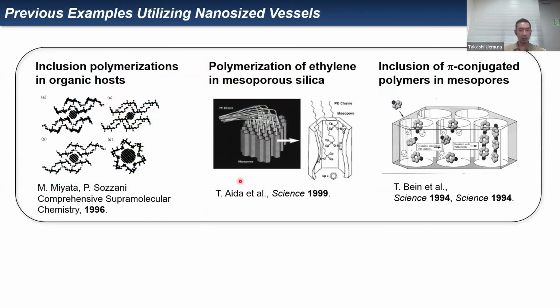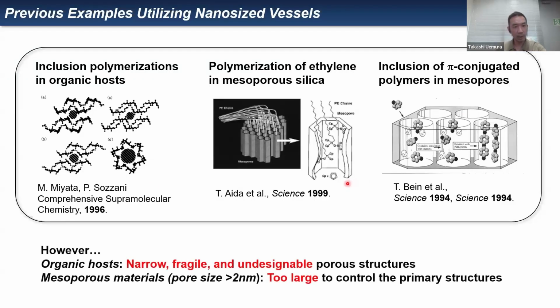Of course, this type of polymerization has already been reported using organic hosts and mesoporous silica systems. However, in the case of organic hosts, it's difficult to apply these host methods to a variety of polymerization systems because of the narrow, fragile, and undesigned porous structures. And in the case of mesoporous materials, the pore size is too large for conventional monomers to control polymer primary structures. So what kind of nano-sized vessels are appropriate for our purpose?